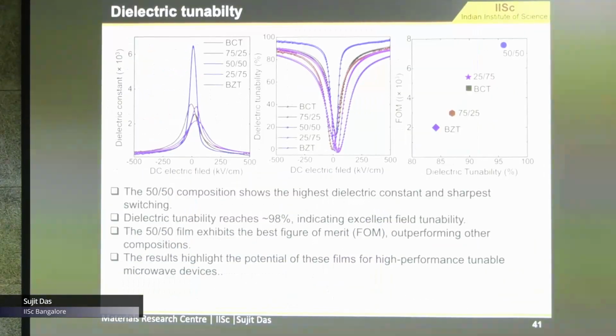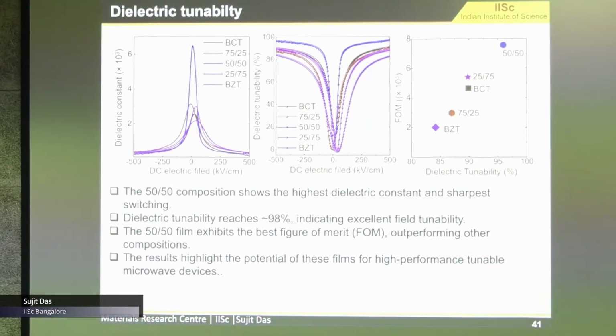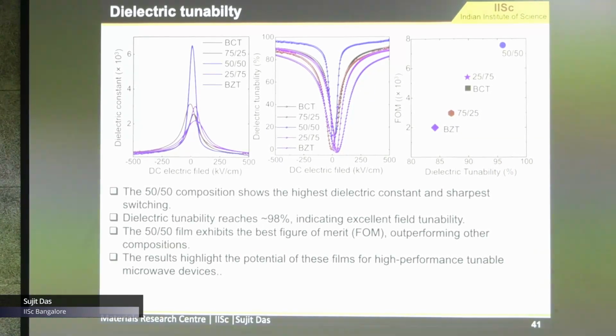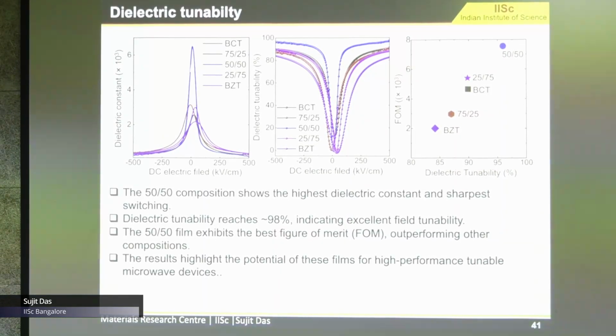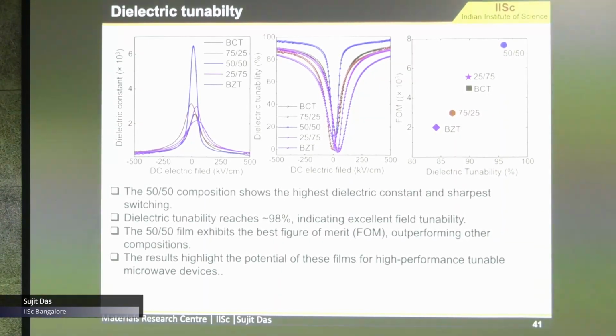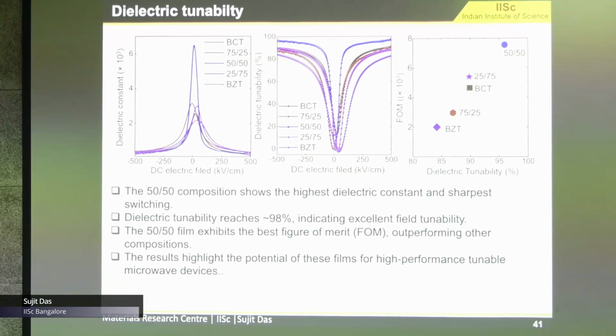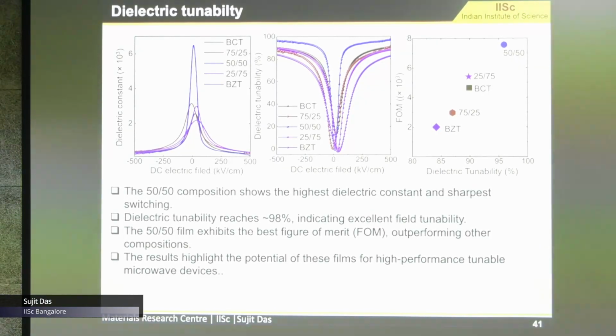Alright, now once we make the device, you can see that for BCT, BZT, the 50-50%, the dielectric constant is almost 6,000, it's pretty high. And once we calculate the tunability from this, we found it is almost 98% at 1 megahertz frequency. The tunability is also very high.